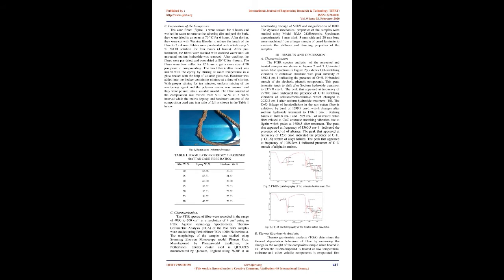B. Preparation of the composites. The cane fibers, Figure 1, were soaked for 4 hours and washed in water to remove the adhering dirt and peel the bark. They were dried in an oven at 70 °C for 6 hours. After drying, they were cut with a Waring blender to reduce the length of the fiber to 2 to 4 mm. Fibers were pre-treated with alkali using 5% NaOH solution for 4 hours. After pre-treatment, the fibers were washed with distilled water until all unreacted sodium hydroxide was removed.